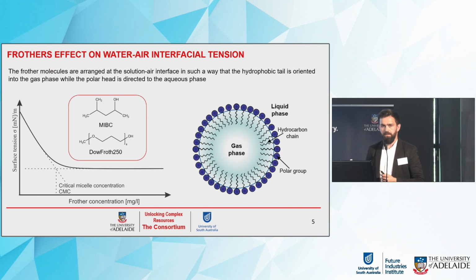And so how can we measure the frother concentration? For that, we can use the interfacial tension because the frother adsorption at the interface results in interfacial tension reduction. And as frother concentration increases, the interfacial tension decreases. And for our investigations, we have selected two frothers which are commonly used, that is MIBC and DowFroth250.